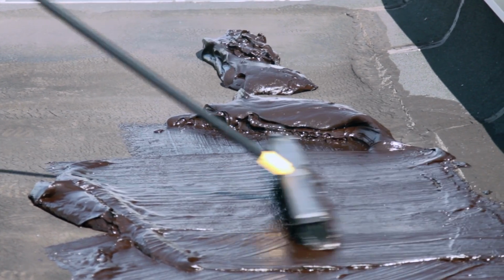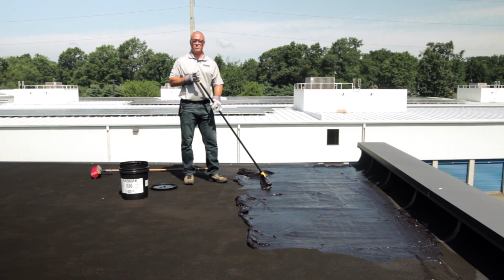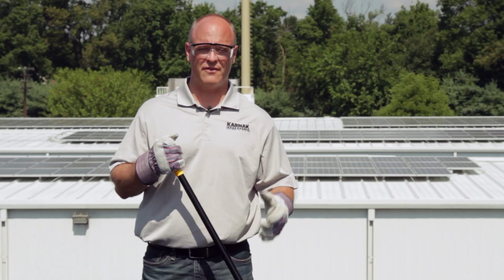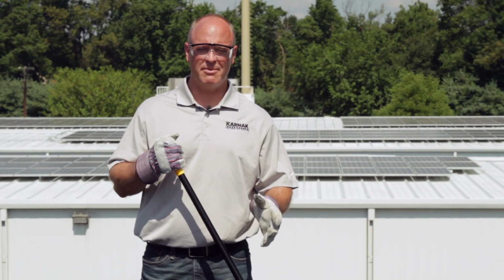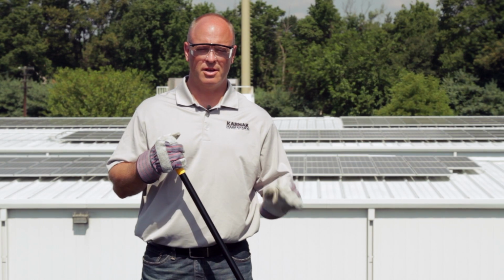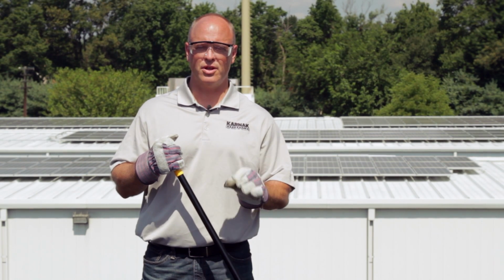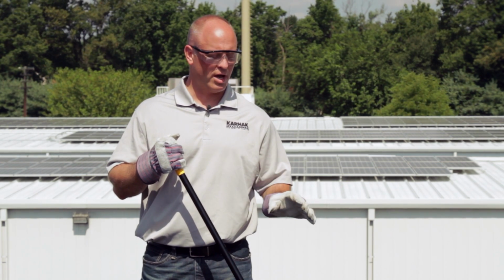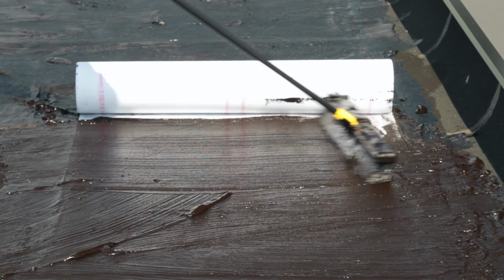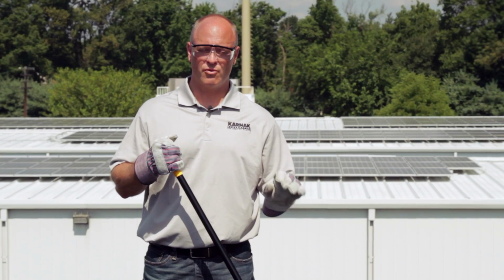Apply the 220 emulsion at 4 gallons per 100 square feet. That's equivalent to about 1/16 of an inch thick. On smooth built-up roofs that have heavily alligatored surfaces or have had an active leak history, it's recommended to reinforce the emulsion coating. We're going to do that with 3036 polymat. That's a great way to strengthen the coating, bridge over the cracks and gaps, and really seal it up.